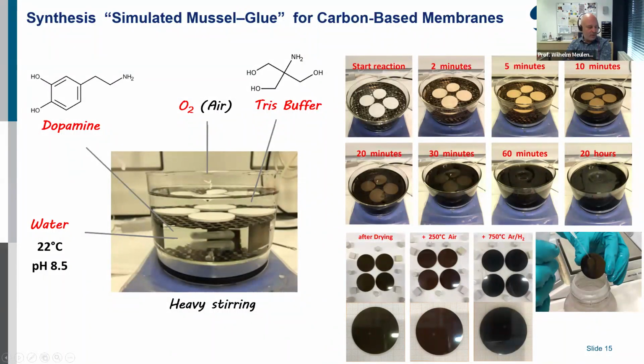And the first idea was to coat our membrane with this dopamine to improve the attachment of this membrane layer to the support. Then in a second step, we fired this layer. So we transferred, in principle through different steps in the furnace, this dopamine also to a carbon layer on top of this graphene layer. And it looks very nice. It has a very good structure without failures.